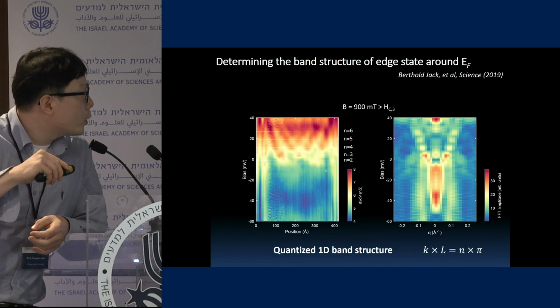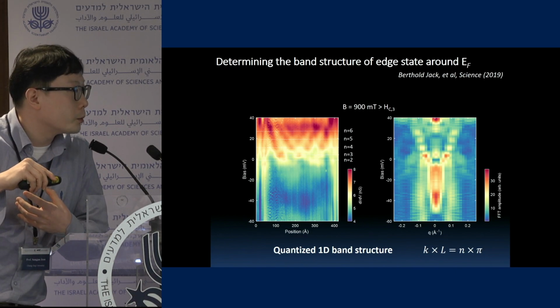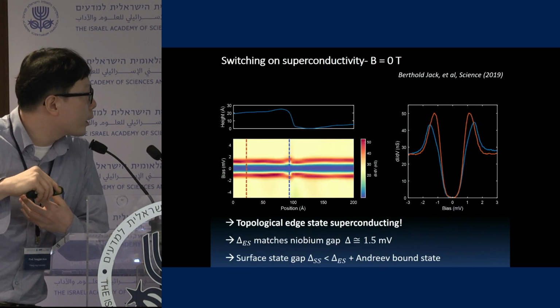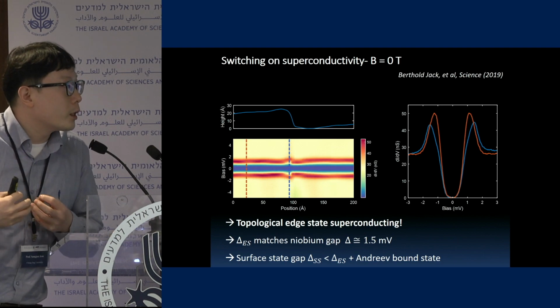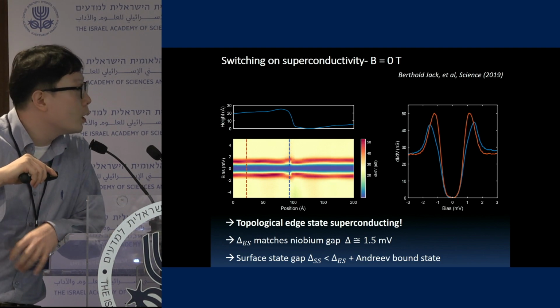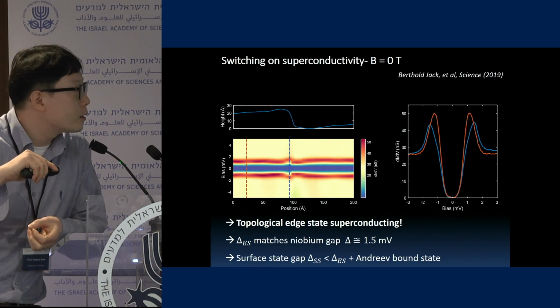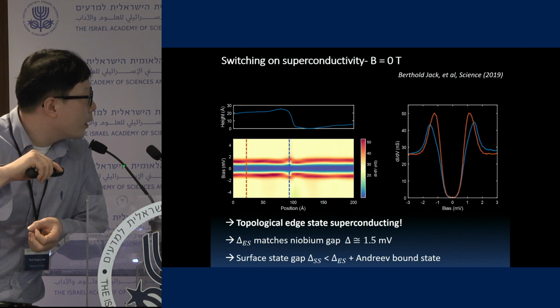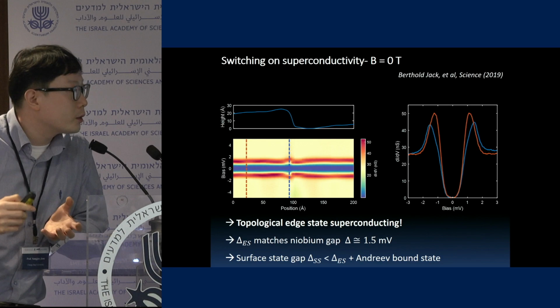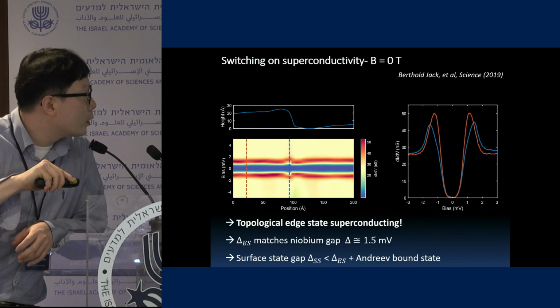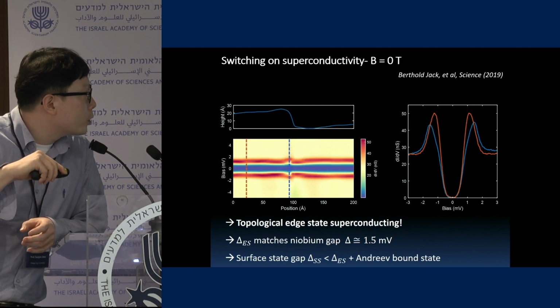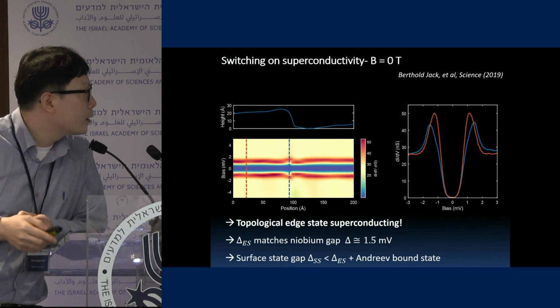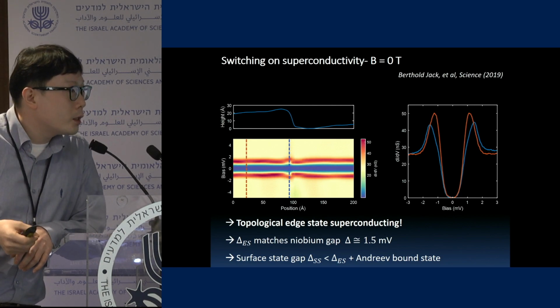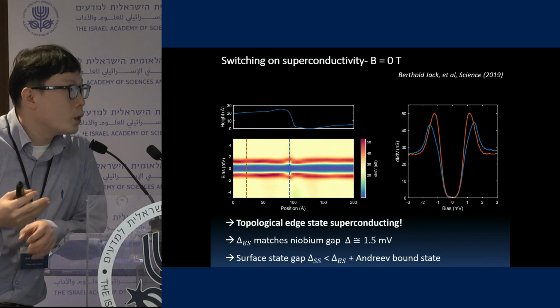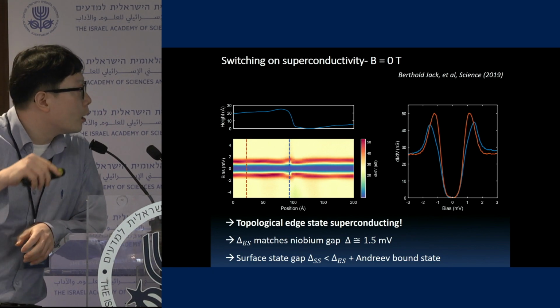And later, here we turn on the magnetic field to suppress the superconductivity of the niobium. But once we have zero magnetic field, you will get a superconducting gap, which is actually proximitized, inducing superconductivity on the bismuth surface and bismuth edge states. Here is the location of the edge, and you see the gap size is different. The red one is the superconductivity at the surface side, and the blue one is superconductivity induced in the edge states. There is some difference in there. So we successfully induced superconductivity in the system with a one-dimensional helical state. That was our understanding here.